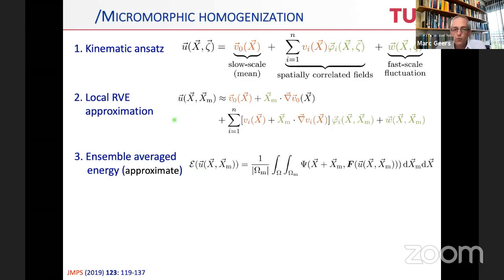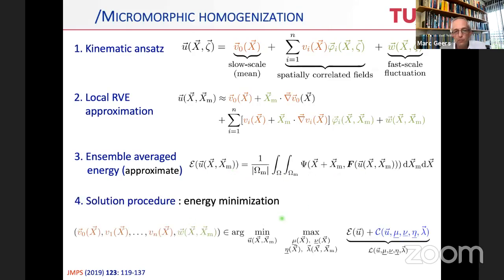To make it clear, we're applying this to hyperelastic materials, actually the hyperelastic material proposed by Katja Bertoldi herself, for which she also determined the material parameters. For that reason, we focus on the energy and its minimization. So the ensemble averaged energy is determined, and we do the minimization process to back out the solution. The minimization of that energy plus a constraint potential, which involves Lagrange multipliers, which I'll detail on the next sheet, allows you to obtain the solution. And what is the solution? That's the displacement mean field, plus the amplitudes of the different modes present in the microstructure, and the remaining part is the unresolved fluctuation field.